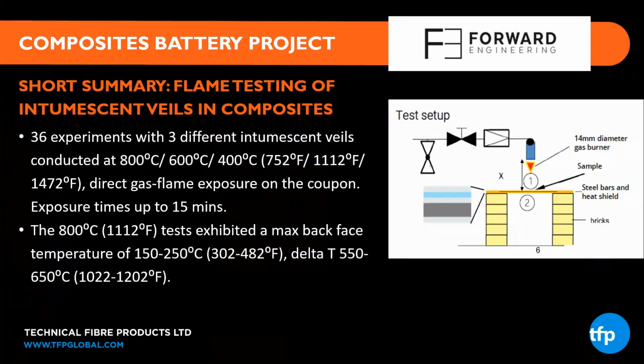And as a brief summary, the 800 degrees C or 1470 degrees Fahrenheit experiments exhibited a maximum back face temperature of 150 to 250 degrees C or 300 to 480 degrees Fahrenheit. So a temperature reduction of 550 to 650 degrees centigrade or 1000 to 1200 degrees Fahrenheit through the insulating action of the Technofire intumescent layer.